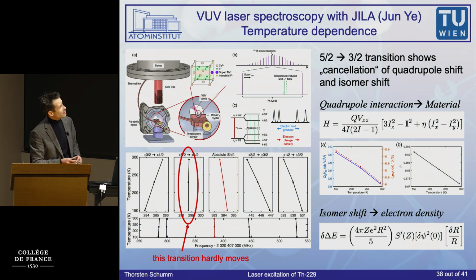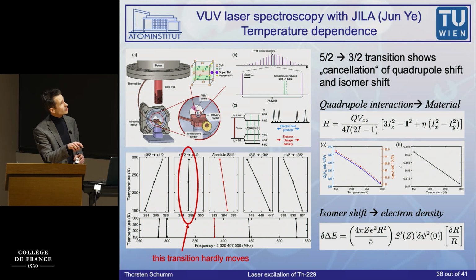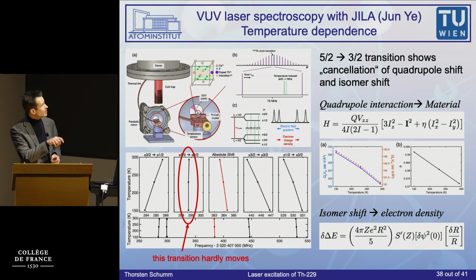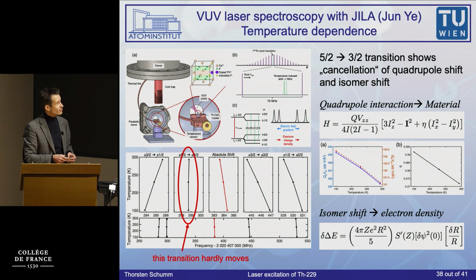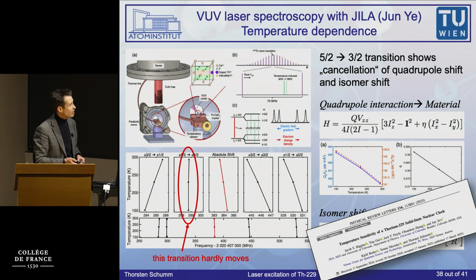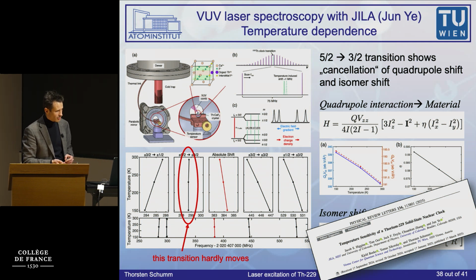That's an effect because there is a quadrupole interaction, which I tried to explain, which is this splitting here. There's another shift, which is the so-called isomer shift, and for this specific transition, these two go in opposite directions and kind of cancel each other. So this might be an interesting transition to use for a nuclear clock, and that was actually published this Monday.